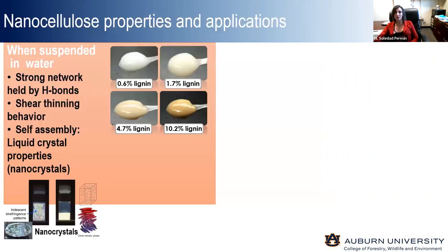So in terms of properties of nanocellulose, and I will make a note that when I say nanocellulose, in reality we usually have a combination of nano and microfibers all together. But what you can see here in this four spoons is a nano/microfibrillated cellulose at about 2% solids. Suspended in water, it will form this very strong network that is held by hydrogen bonds that has a very particular flow behavior. It's shear thinning, meaning that it flows under shear, and it's a very appealing property if we think about coatings, for example.